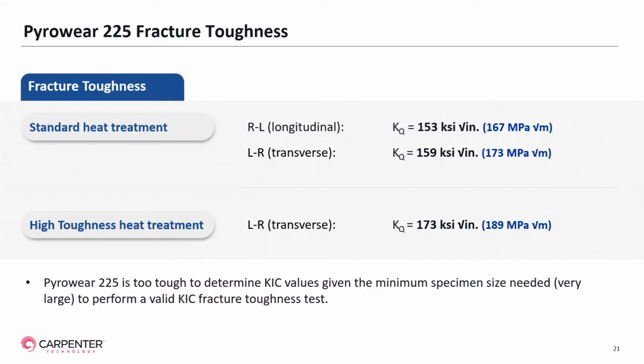The fact is, Pyrowear 225 is too tough to determine the true and valid K1C values given the minimum specimen size needed, which is very large, to perform valid K1C fracture toughness testing.